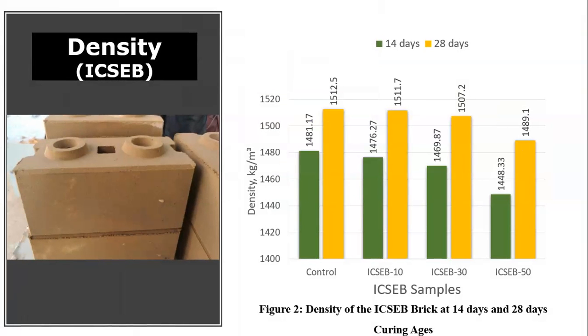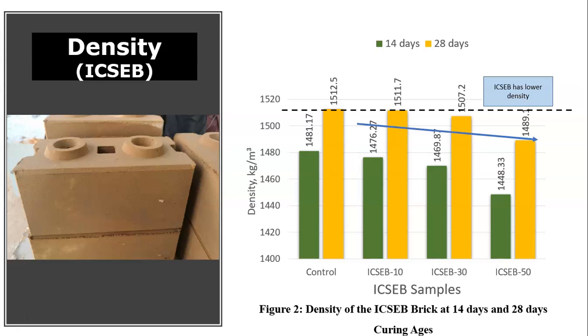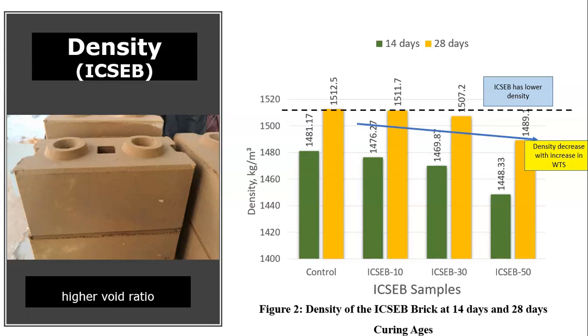The density of the ICSEB is shown in figure 2. A similar trend was also observed for all ICSEB samples cured at 14 and 28 days period of curing. And this may be due to the sludge, which gives a higher void ratio. Hence, an increase in the amount of sludge in brick will reduce the brick density.